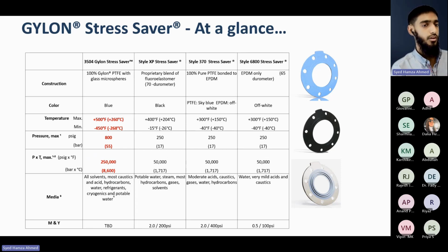We do have a proprietary blend fluoroelastomer gasket by the name of style XP stress saver. Again, we have rubber models, which is the EPDM model stress saver. Also, we do have 100% pure PTFE bonded to EPDM, that is the style 370. These gaskets generally go from 150 degrees Celsius maximum operating temperature to 260 degrees Celsius maximum operating temperature, and pressures can range from 250 up to 800 psi gauge.